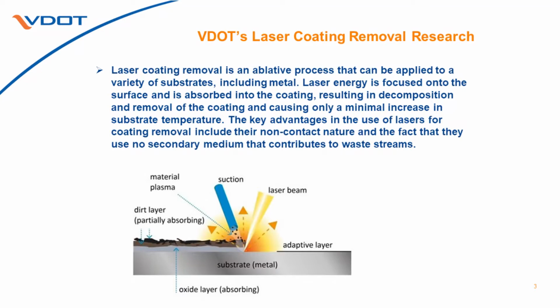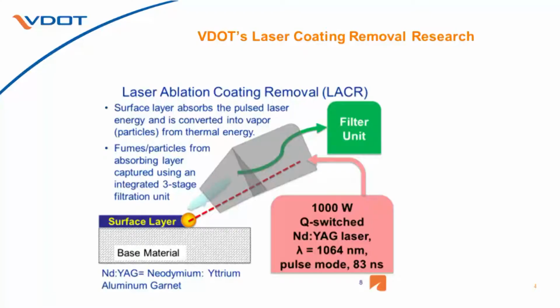It's a little bit of the theory about how the laser coating removal works. It's an ablative process that can be applied to a variety of substrates, including metal. Laser energy is focused onto the surface and is absorbed into the coating, resulting in decomposition and removal of the coating and causing only minimal increase in substrate temperature. The key advantages in the use of lasers for coating removal include their non-contact nature and the fact that they use no secondary medium that contributes to waste streams, aka there is no blasting media that has to be disposed of. Basically, the surface layer absorbs the laser energy and is converted into a vapor.